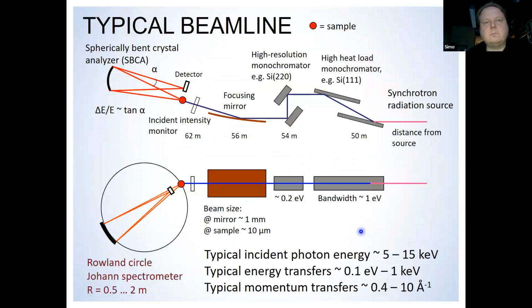So because it's useful, I would like to show here a typical beamline setup. This is a view from the side, and this is a view from the top of a typical beamline. You prepare your incident beam, focus and monochromatize it, and hit it on the sample. And then you have a crystal analyzer spectrometer, which in X-ray Raman is often based on the so-called Johann geometry. Basically, on a Rowland circle, you have a spherically bent crystal analyzer that then focuses the radiation onto a detector, and selects the wavelength through Bragg's law.